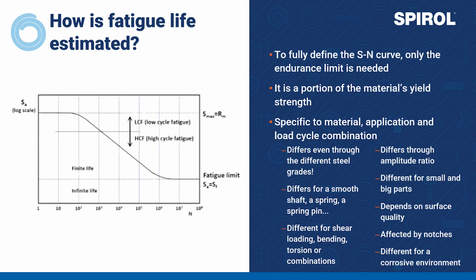Well, to fully define the SN curve for something, we only really need the endurance limit. On the previous slide, we learned that the low cycle strength is not much different from the material's yield strength, and that it kind of drops to the endurance limit after 1 million or so cycles. So the endurance limit is always a portion of the yield strength, and it is specific to material, application and load cycle combination.